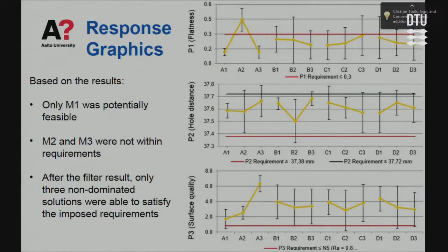So looking at the initial results that you can compute from the objective functions of the Taguchi experiment, you can immediately see that here is flatness, hole-to-hole distance, and surface quality, and this is the requirement. So values, which means these are mean values for machine 1, machine 2, machine 3, horizontal, vertical, diagonal, right, left, center, so you can see all the parameters. So, for example, looking just at the flatness, machine 2 is out of specification, so we drop that machine. That machine cannot be used.